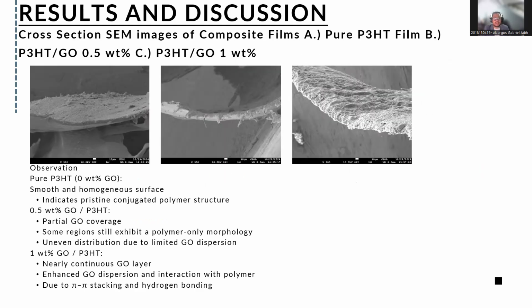Then for the cross-section SEM images of the composite film, which are the pure, the 0.5 weight% added GO, and the 1 weight% added GO. For observation, we will have a smooth and homogeneous surface, which indicates a pristine conjugated polymer structure on the pure one. Once we added the 0.5 weight% GO, we will see the partial coverage of GO, while some regions will still exhibit a polymer-only morphology. There's also an uneven distribution of GO due to the limitation of the dispersion.